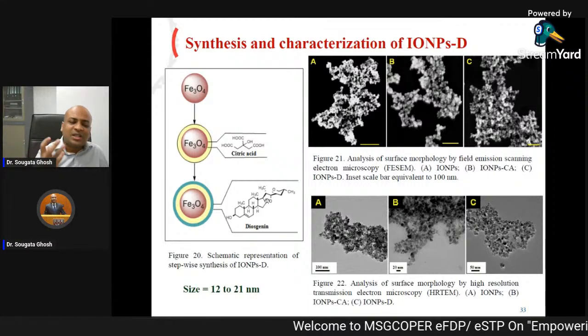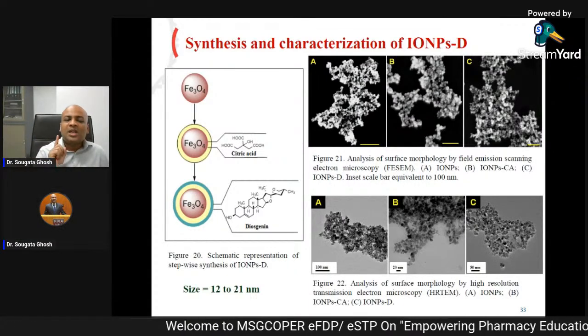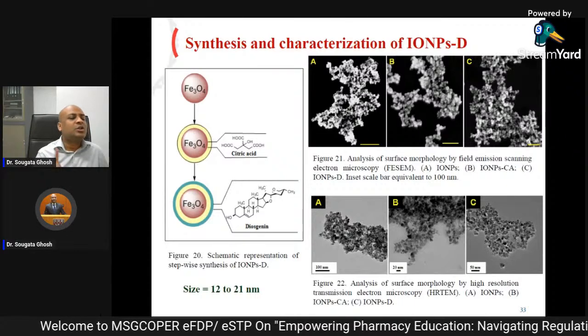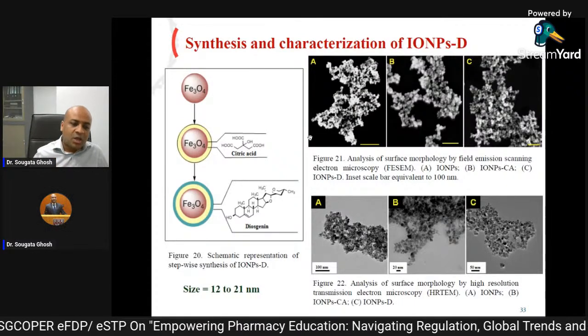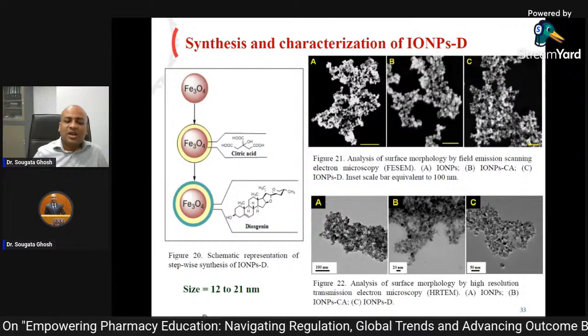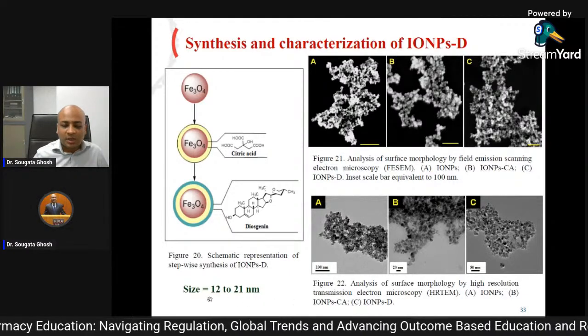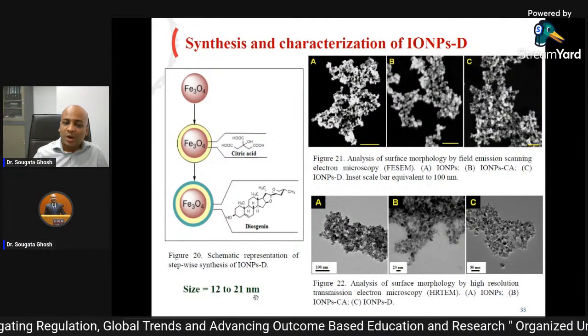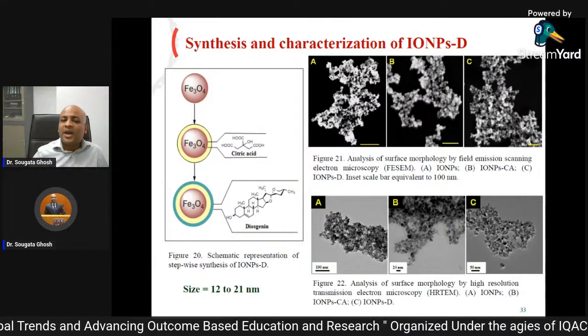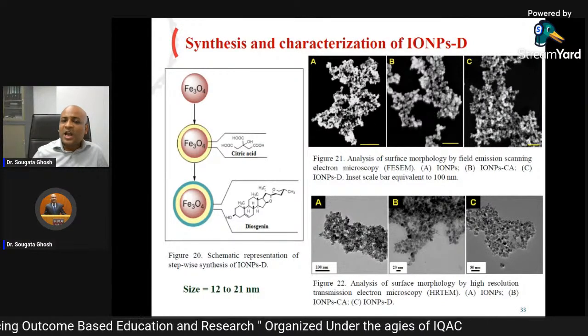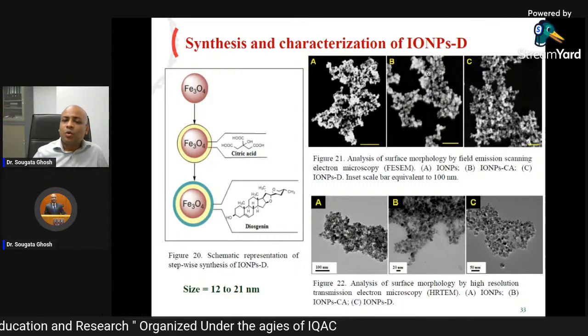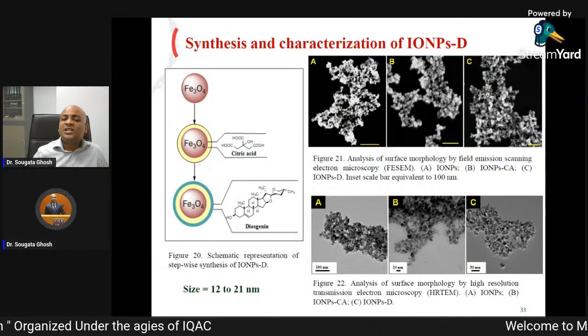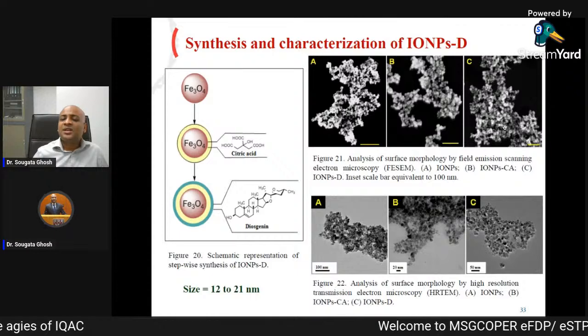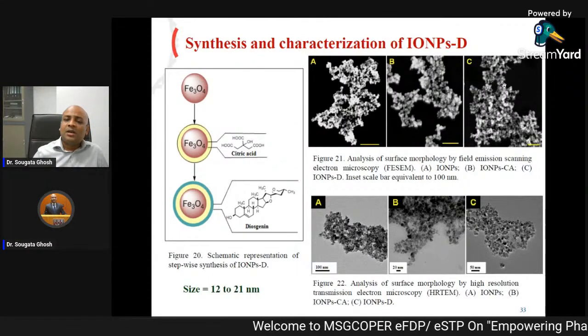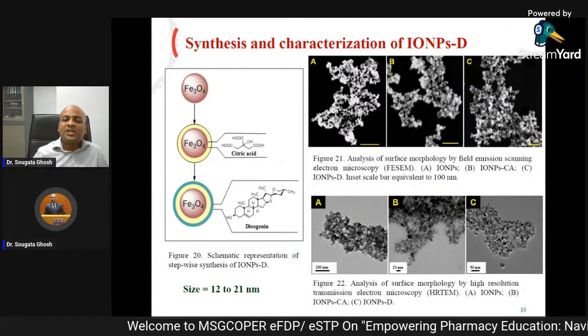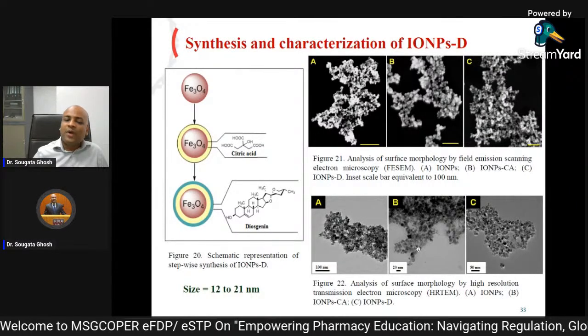Now, this diosgenin is such an important component. It knows it can go and kill only the cancer cell and it will not kill the normal cell. The size of these nanoparticles ranges from around 12 to 21 nanometer. So you can see this is bare iron oxide nanoparticle. This is citric acid coated iron oxide nanoparticle. This is diosgenin functionalized citric acid coated iron oxide nanoparticle. We did the HRTEM analysis similarly and we found these structures.